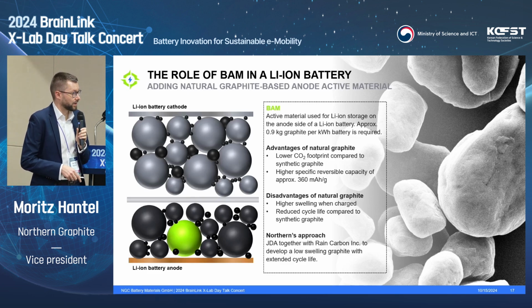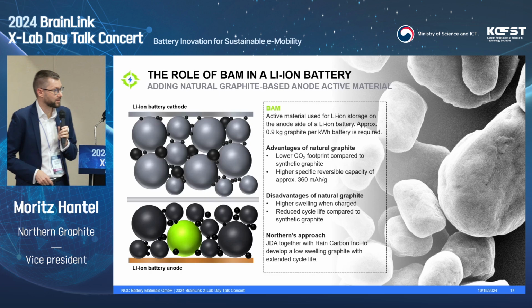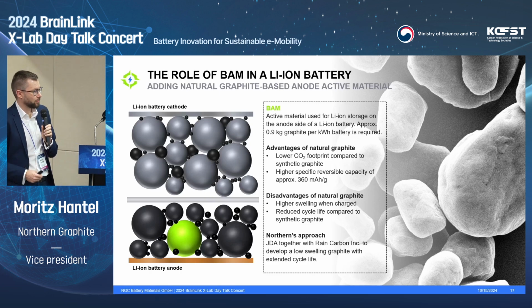And that's one thing I can mention at the moment. We're working here together with Rain Carbon. The JDA was announced last week officially, where we are working especially on the coating side, where we have seen that tuning the coating can mitigate issues from swelling and cycle life, and getting a natural graphite-based material very close to a synthetic graphite one.